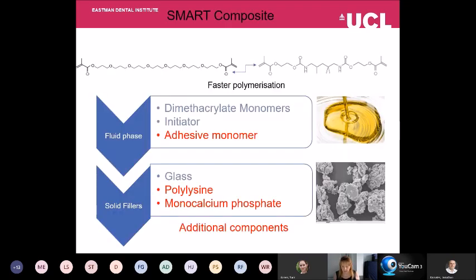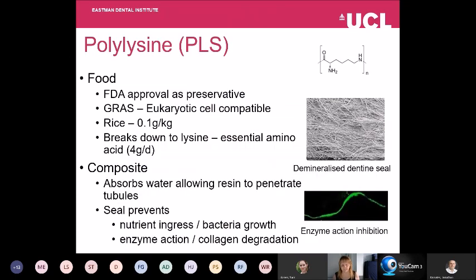The other components that we've added in, first of all, we've added in an adhesive monomer. So this is the monomer that we find in the primers, and that helps us to get some bonding to the tooth structure. We've also added in 2 other components that we find in food. First is polylysine, and the second is monocalcium phosphate. Now these we've actually only had to add in low levels, but they make a really big difference in the way that the material interacts with dentine.